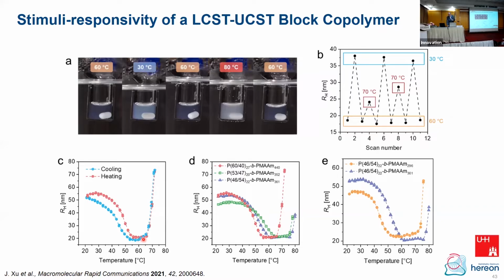And when we increase the temperature further, we go into the LCST, and again we get micellization. Depending on the composition of the random copolymer block, the LCST can be adjusted. So we can switch the hydrodynamic radius as a function of temperature, but now in two directions. At low temperature, we get aggregation. At high temperature, we get aggregation. And somewhere in between, we have a window of nicely dissolved polymer.